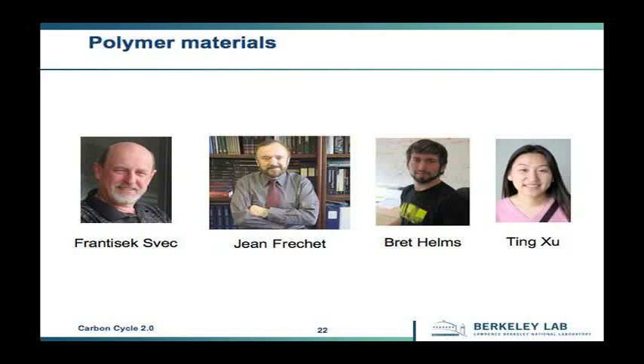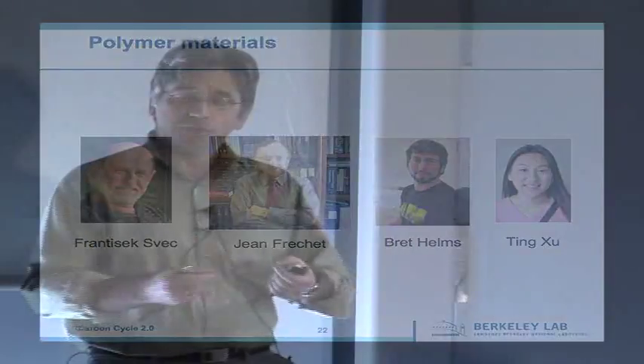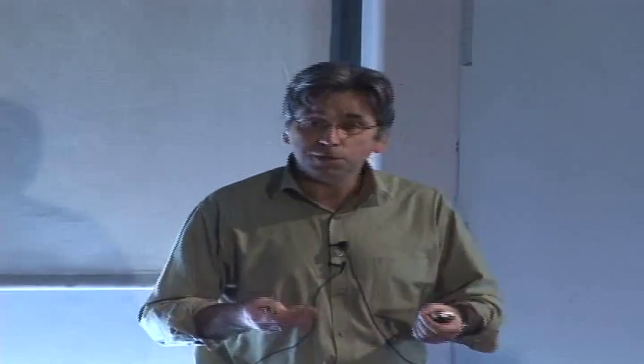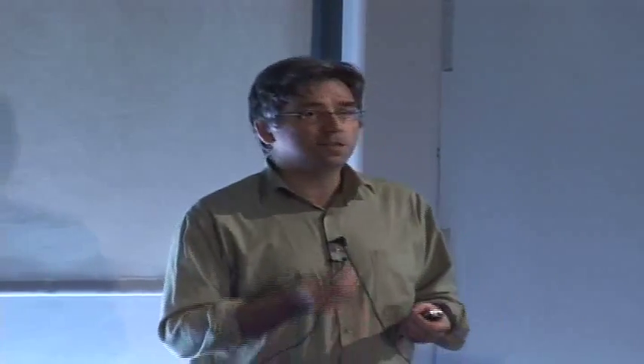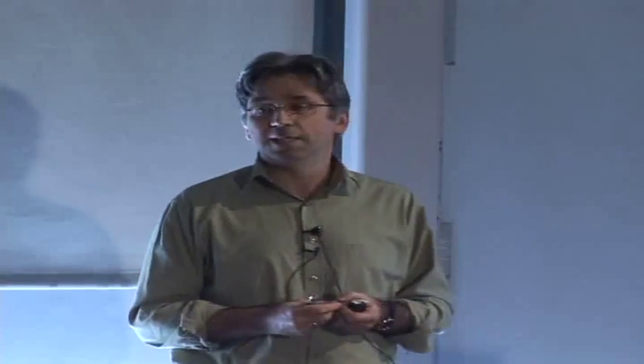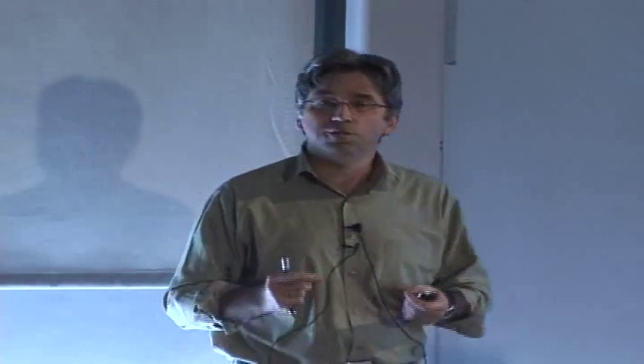The membrane people are Ting Xu, Brett Helms, Jean Fréchet, and Frantisek Svec. And what they try to do is to make a polymer membrane. So polymer membranes are already used for CO2 separation, but with the type of membranes they actually make, it's very difficult to have a well-defined control over the pore size. And that is, of course, what you would like to do. You would like to make materials in which you can exactly control the pore size for optimizing the separation and then introduce some additional chemistry to enhance the selectivity.